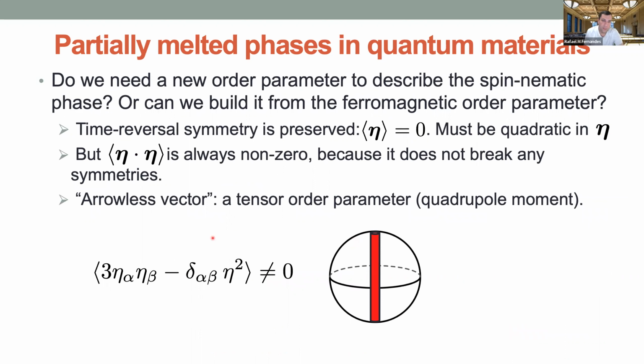So it is different. I think the example would be the equivalent of here. Because what you're describing are amplitude fluctuations or phase fluctuations—they do not break any symmetry. They are present at any temperature. Of course, they build up as you get closer to TC, but they are not a symmetry-breaking fluctuation channel. On the other hand, this particular combination that I had here does break a symmetry. So you can think of these as fluctuations that break symmetry. It's an abuse of language, but it's beyond just fluctuations—they're connected. You're going to need these isotropic fluctuations to get this order parameter to condense, because these are also fluctuations. But you can separate the fluctuations into different channels if you wish. Okay, I see, thank you.